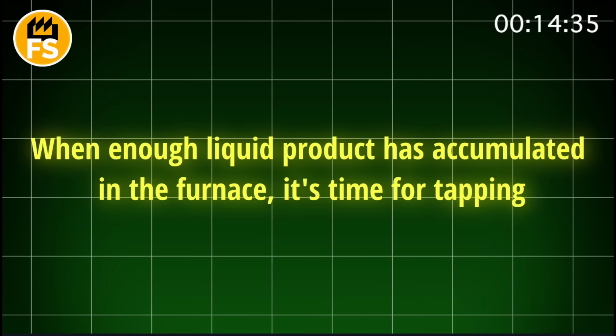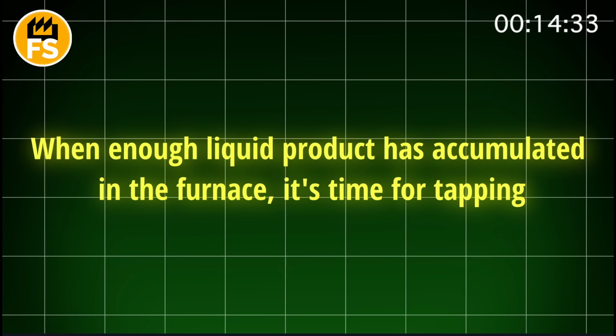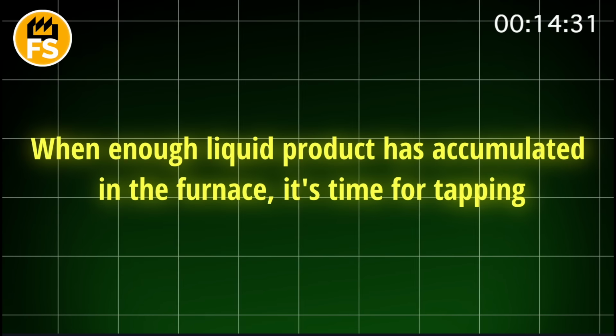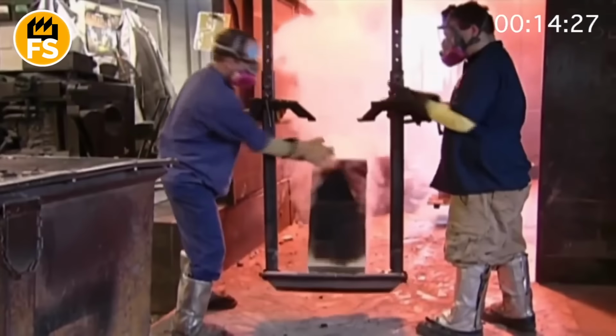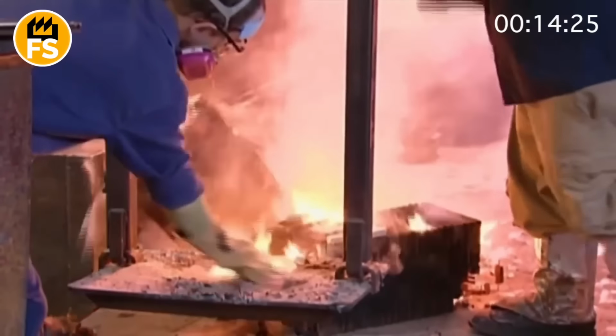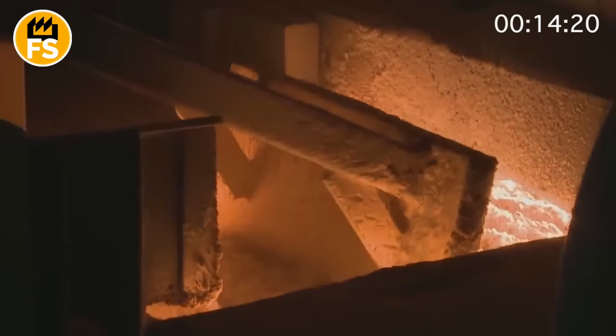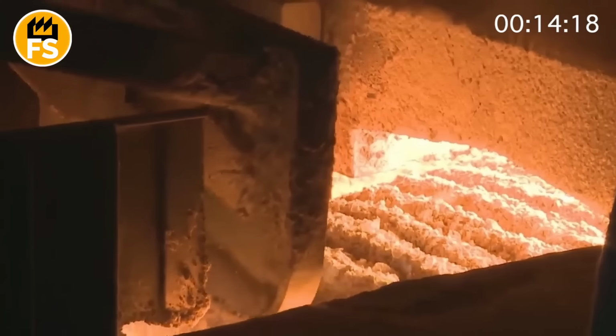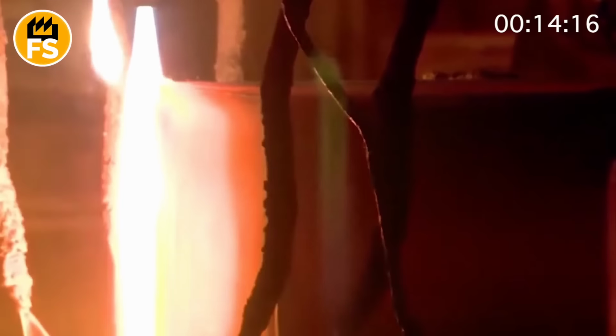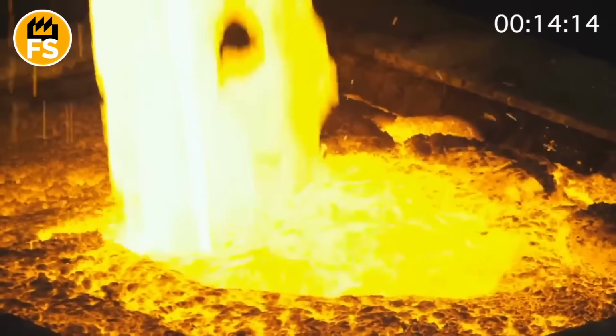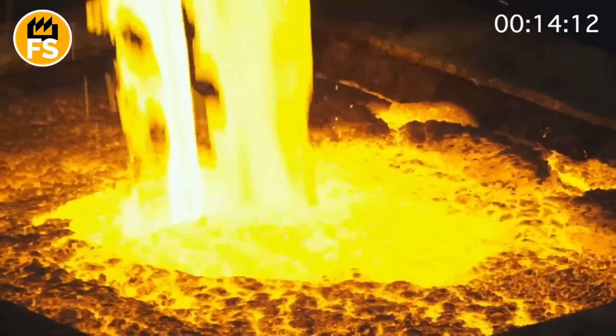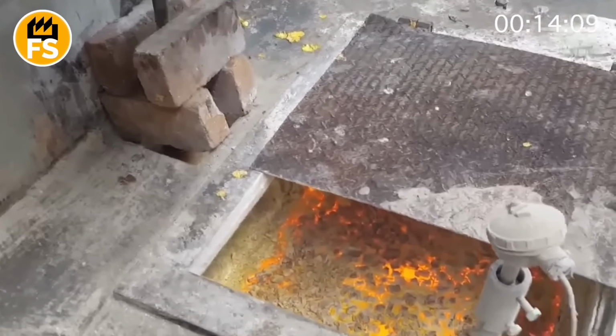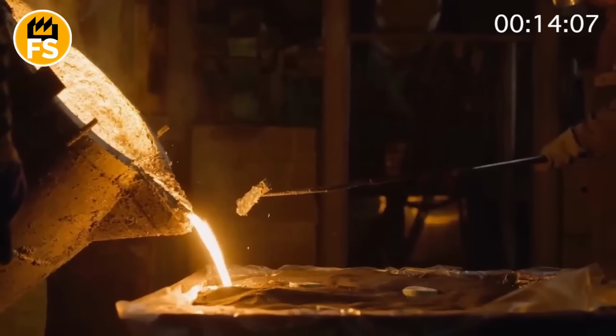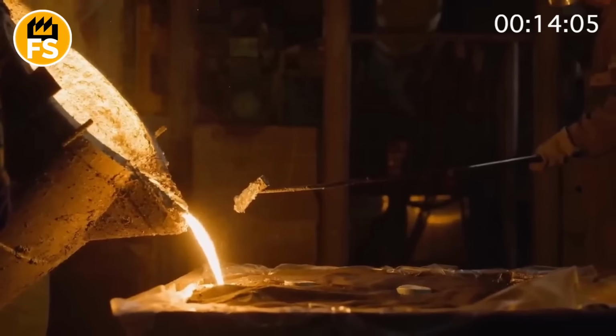When enough liquid product has accumulated in the furnace, it's time for tapping, the most spectacular moment. A worker, using a special tool, or even a small directed explosion, pierces a hole in the lower part of the furnace, called a tap hole. From there, with a deafening roar and a fountain of dazzling sparks, a stream of white-hot metal erupts. This fiery waterfall is directed into a huge ladle. Since the slag is lighter, it flows out next and is poured into another ladle or a special slag pot.